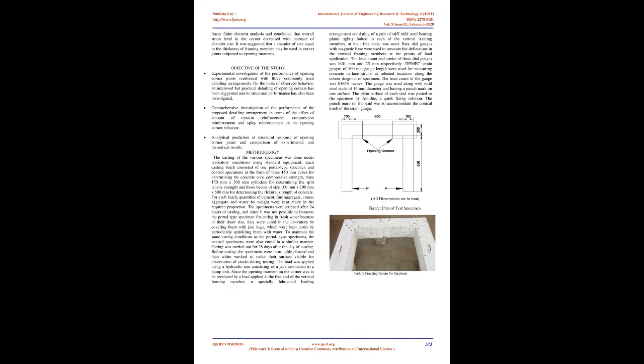Abdul Wahab and Salman, 1999, investigated the effect of corner angle on the efficiency of reinforced concrete joints under opening bending moments. 12 specimens with 2 reinforcement details and the included angle varying from 60 degrees to 180 degrees were tested. It was concluded that corner efficiency was significantly influenced by the corner angle. The minimum efficiency was observed for the corner angle of 120 degrees. Further, the use of splay steel at the corner significantly improved the corner efficiency in the range of 56 to 100% for different corner angles.